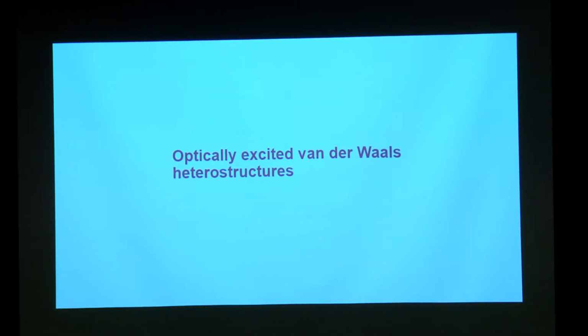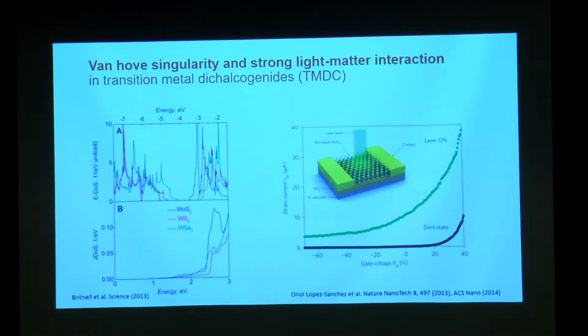Let me tell you what I mean by that before we get into the details of this experiment. First of all, the transition metal dichalcogenides are semiconductors, but they have a very special property. These materials can absorb light in a hugely efficient manner. That's primarily because right at the band gap there's a huge optical density of states, which helps them absorb nearly 30% of the optical radiation, even when the layer is just one monolayer thick, maybe just 0.3 nanometer. So even one monolayer of these chalcogenides, which is essentially a chalcogen atom, sulfur or selenium or tellurium, on the other side, are extremely efficient light to electricity converters.